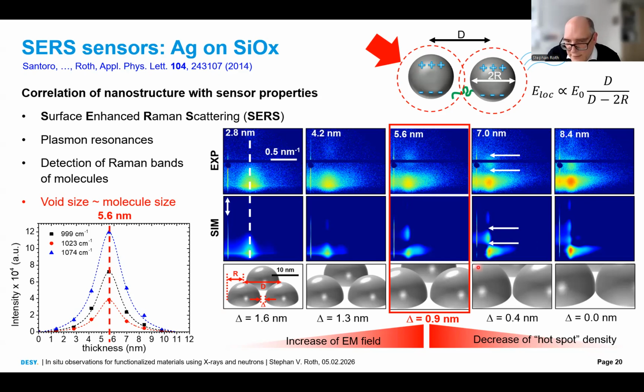If you look at the intensity here, the intensity is concentrated in this line, and here the intensity shifts upwards. This has to do with the Yoneda peak. Then you see a layer of a higher density. This is basically the silicon Yoneda peak, and then this is the silver Yoneda peak. So you see a rough layer of silver, a full layer with a roughness. This is here the shifting of the intensity.